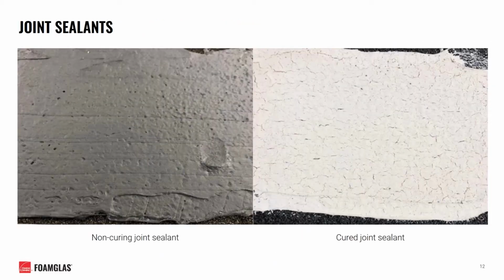The benefit of using a non-curing joint sealant in these types of applications is really highlighted in these images. Both of these materials were held in an oven for a period of time and then evaluated for their physical properties afterward. A non-curing material, like on the left, won't dry out and will maintain its stickiness, which you can see in the thumbprint on the right side of that image. Other materials will dry out and crack, which can offer a weak point for moisture to enter the system. As we talked about, FOAMGLAS insulation is impermeable, so that would be the only permeable point of the system. So it's important to keep those joint sealants flexible and able to keep those joints closed.